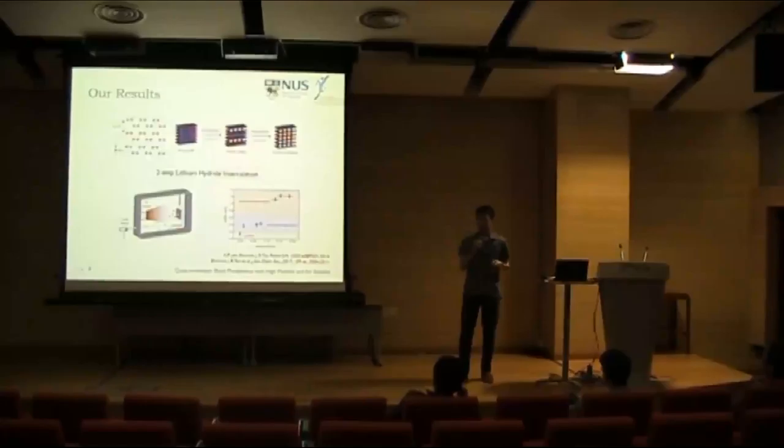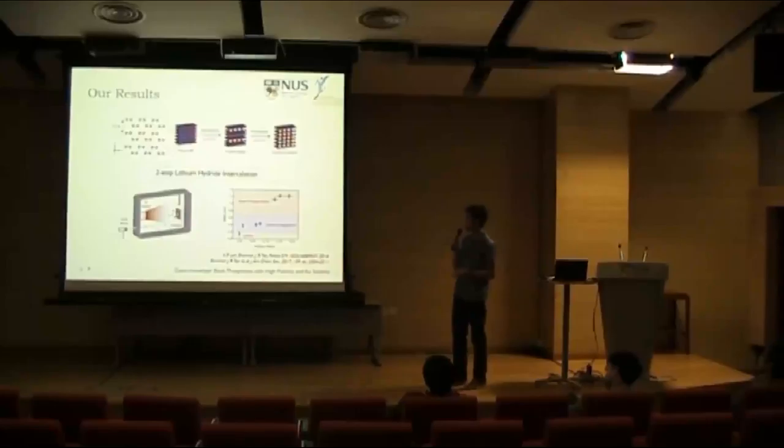And so what our group has done previously was we invented a new method by confining a chemical reaction in between 2D materials. And we have found that using a hydrogenation method, we can stabilize a large class of TMDs, which is another 2D material. And the chemical reaction is upscalable as it's very simple. We just need a lithium source and then we intercalate the lithium in the material and then we hydrogenate it.